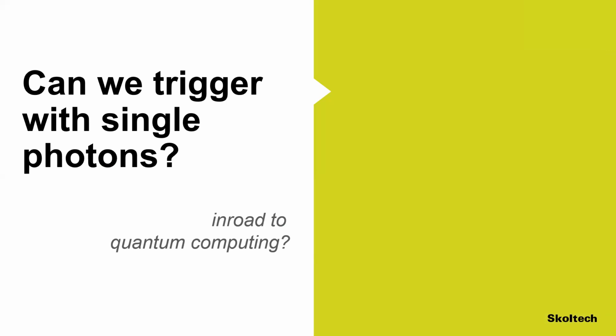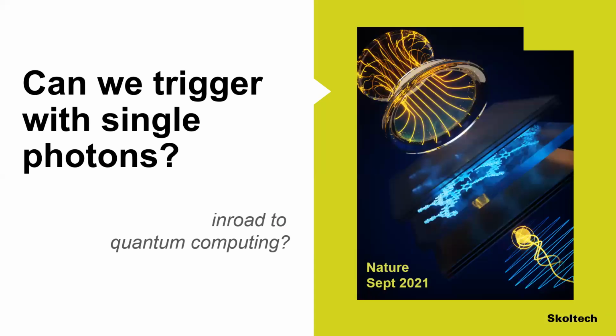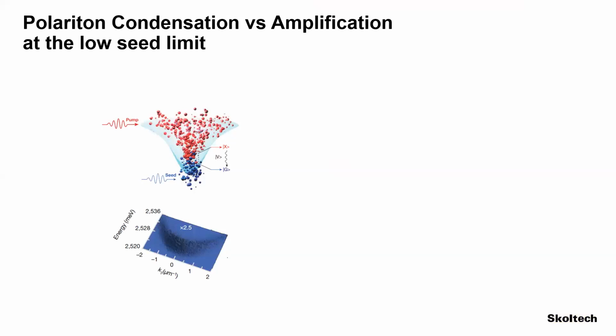So in 2021, we managed to tune the structures and all the optical setup, which Professor Kilin has seen actually at Skoltech. It is a mammoth setup. But really what we could show is that by tuning the structure with vibron resonance in an optimal way, we could create, this is the emission of the condensate, this is dispersion, in-plane momentum and energy.